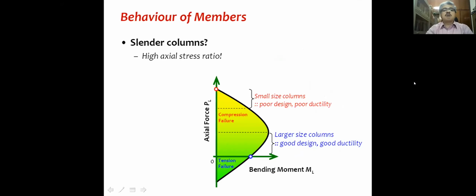This is something that we need to watch out for when we use high strength materials for our constructions. Smaller houses may not need use of these high strength materials. So small size columns designed this way are going to have compression failure as the failure mechanism. Rather, we should go for larger column size so that the axial stress level is within limits, below the balance point, ideally, but need not be necessary for all cases under all load cases.